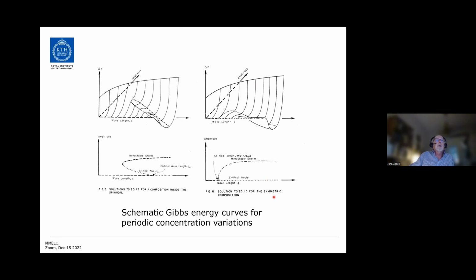Then it turns out that below this point, if you increase the amplitude, it will just go up. But then there is a critical point here where you get a minimum, and you can see it here as a valley. So from this critical nuclei can now move down in this valley and have a continuous decrease in Gibbs energy. And this is inside the spinodal, but not in the middle. And now you can see that there is a barrier here which you have to pass before you come down to this valley. So these are maximum points, and those are minimum points. And here there are only minima.